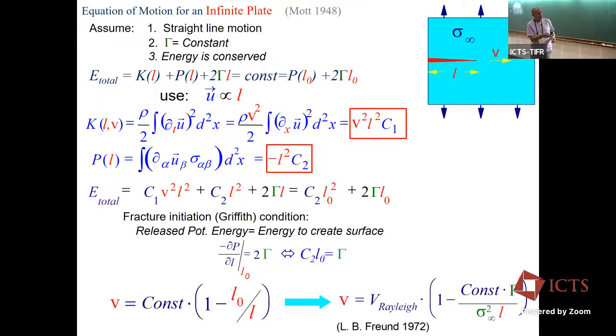Now, if we just shove these into this expression, this is a quadratic equation that even I can solve. So this is the answer. And this is telling us, first of all, that v, the instantaneous velocity of the crack, is equal to some constant, which we'll talk about in a second, times 1 minus L naught, the initial length of the crack, divided by the instantaneous length of the crack. Now, if you actually solve the problem, all of this stuff just has dimensions of length because this is the dimensionless quantity.